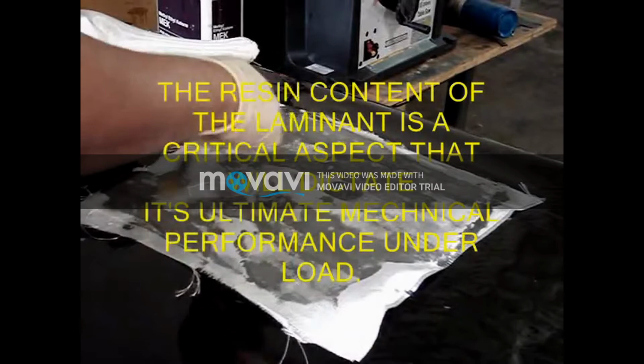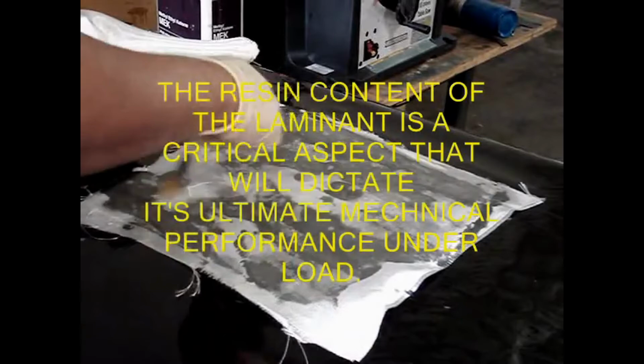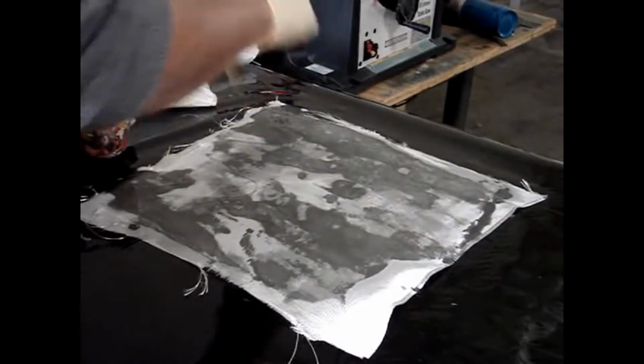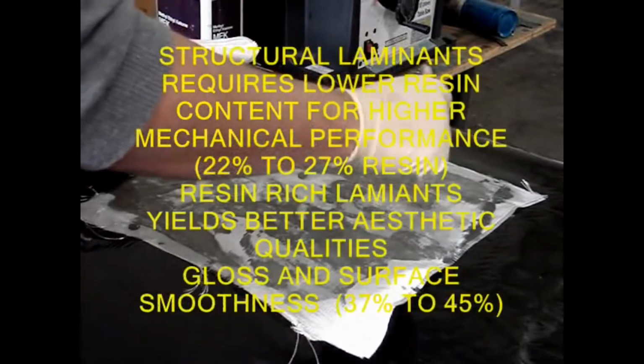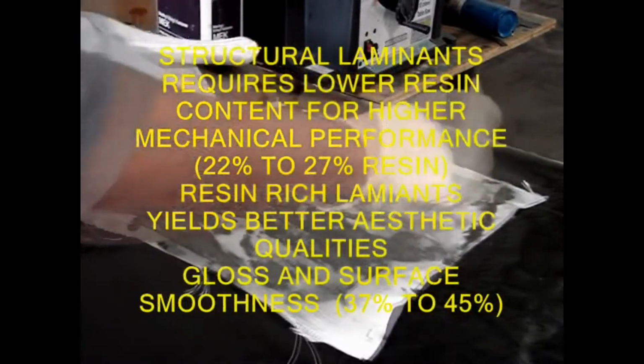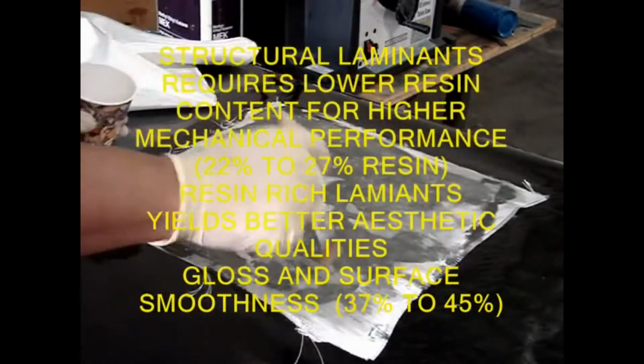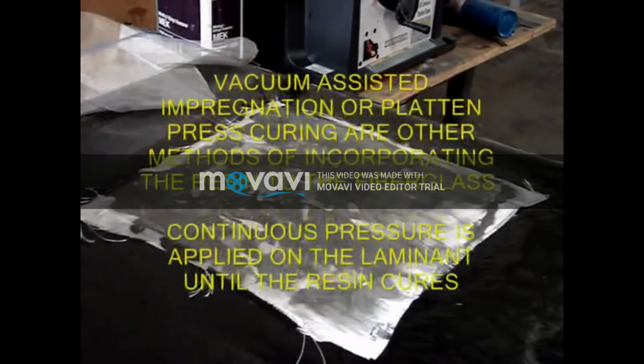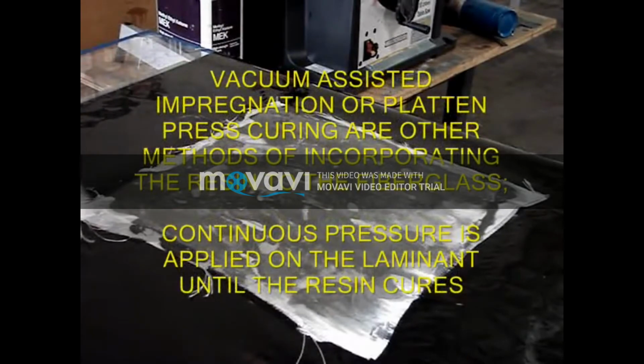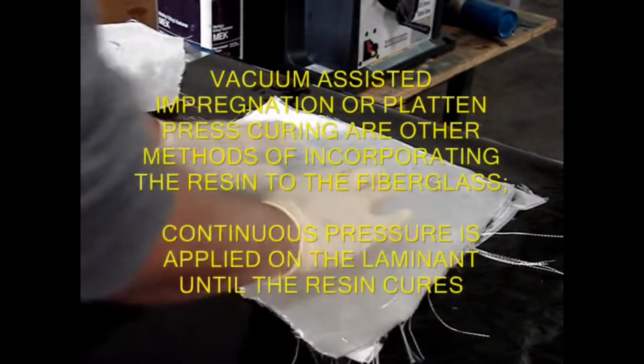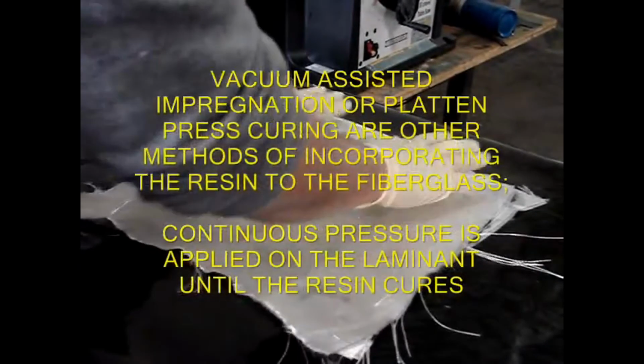The resin content of the laminate is a critical aspect that will dictate its ultimate mechanical performance under load. Structural laminates require lower resin content for higher mechanical performance, and vacuum assist impregnation or platen press curing are other methods of incorporating the resin into the fiberglass.